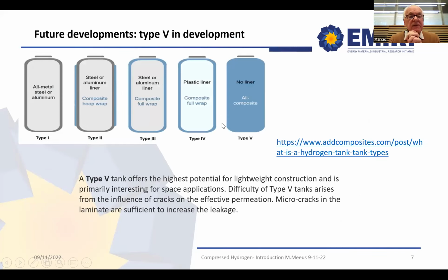But there is a fifth one in development, and that is the type 5, no liner, all composite version. It's not ready yet for commercialization. It offers the highest potential for lightweight construction, and it might be interesting, for instance, for space applications. The difficulty still with type 5 tanks is the risk for formation of cracks and to have an effective solution for limiting and blocking hydrogen permeation. Microcracks in the laminate are already sufficient to start leakage formation.